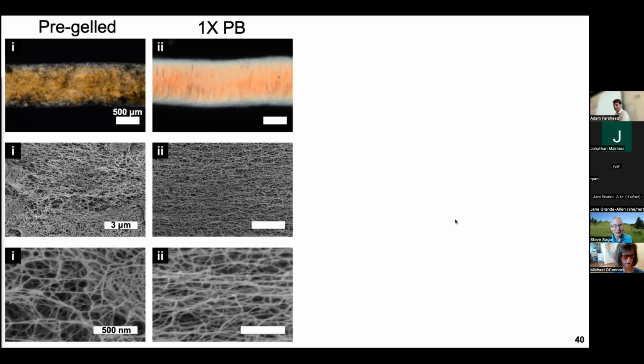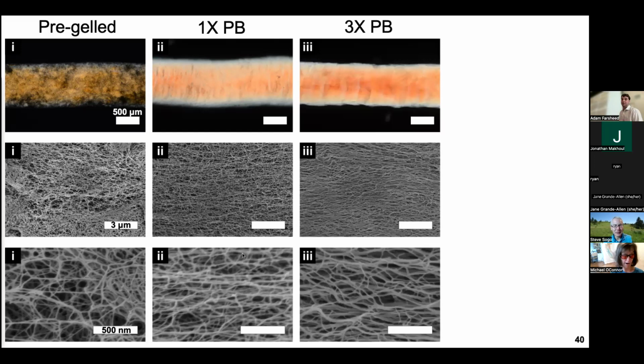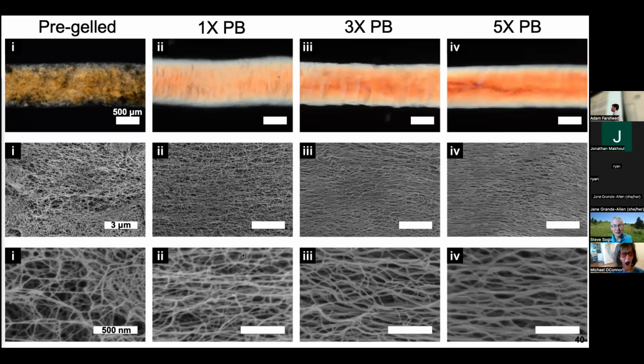And then because we were interested in this region, we are going to introduce these two new gelation baths, which are 3x phosphate buffer. So this is PBS, but you just triple the amount of phosphate buffer. You don't change the salt that's going on in there. And then the 5x case, where you're at 5 times the phosphate buffer concentration. And what we're really able to see, through polarized light microscopy and also by directly observing the fibers, is an increase in that alignment and that birefringence.